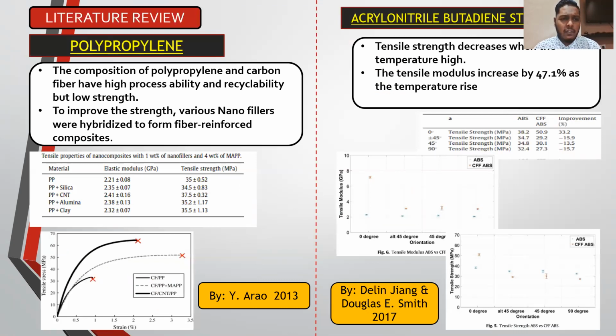For the literature review, we choose ABS because when we compare it to polypropylene, the composite of polypropylene and carbon fiber has high processability and recyclability, but it is low in strength. To improve the strength, we need to add some nanofillers, where it can increase the pressure, and also the flow rate will become low. For the ABS, we can see the tensile strength is slightly lower than polypropylene, but it has a good tensile strength for a repair application.